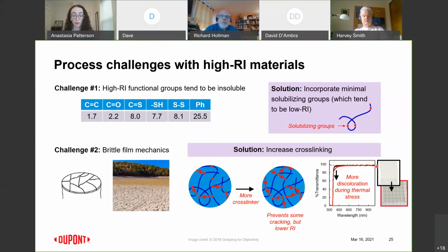But this film is coated, and then that part of the device gets integrated into the whole device, and it undergoes different thermal stresses. The greatest of which you can think of is the solder reflow step. So our film needs to be able to endure the solder reflow temperature around 260 C for a certain number of minutes. And so if we go from the black curve, the original film, and do some thermal stress tests, you can see the effect, the translation of this data is basically a yellowed film. And again, we don't want color in the films.